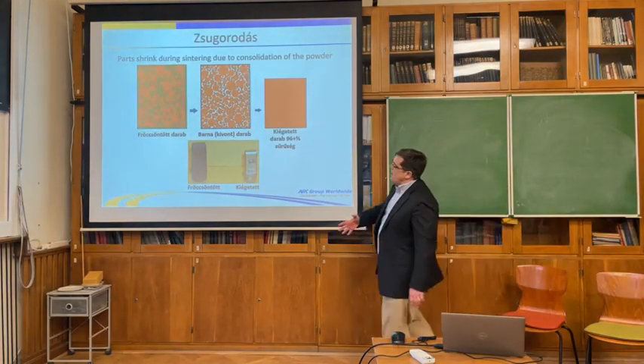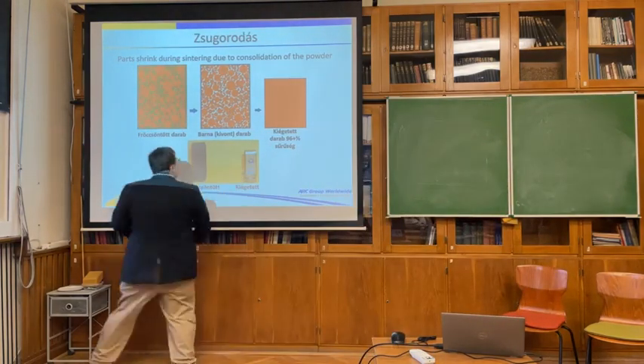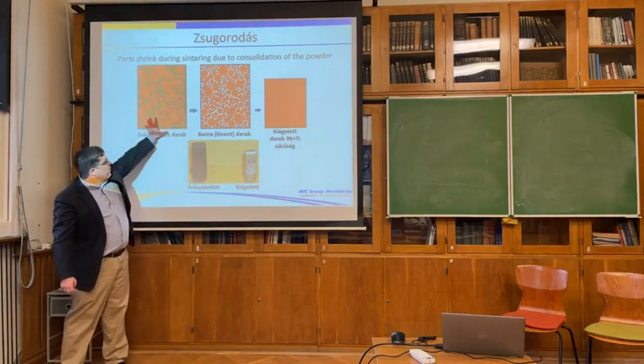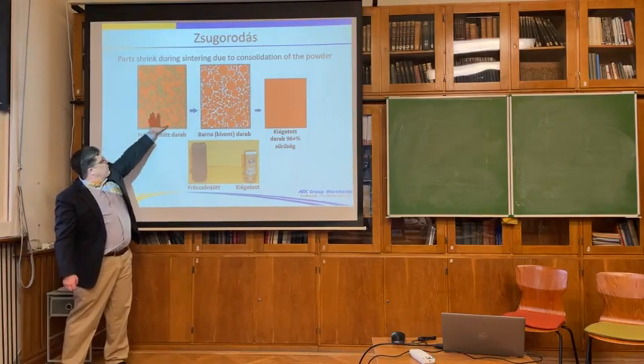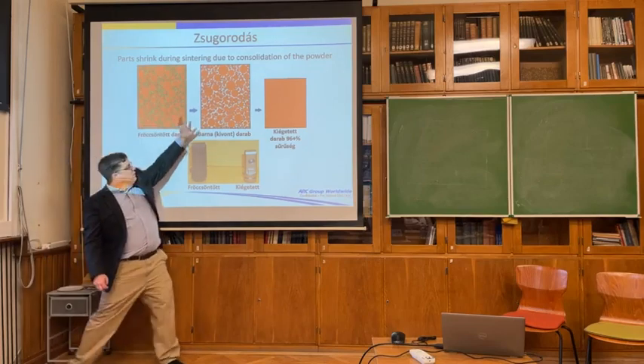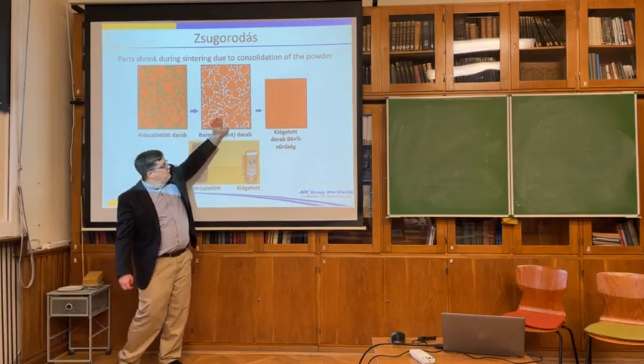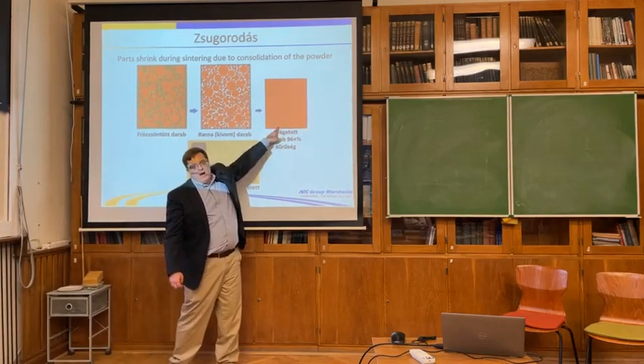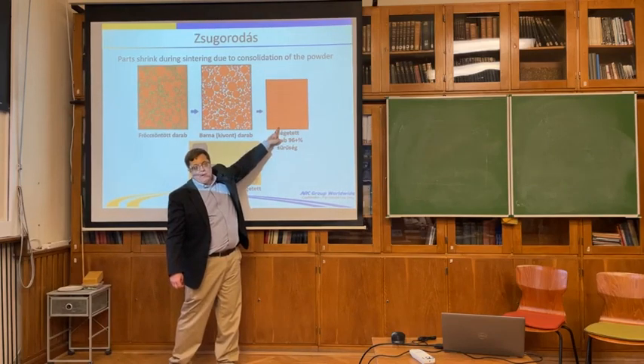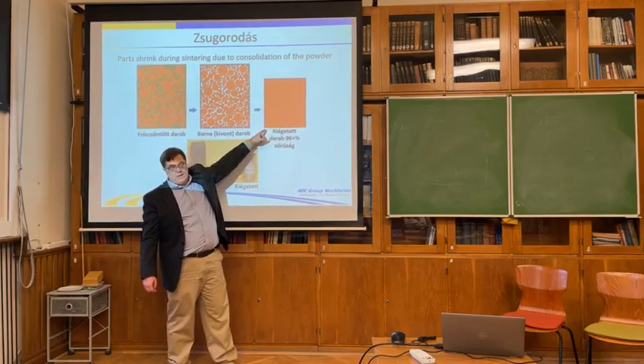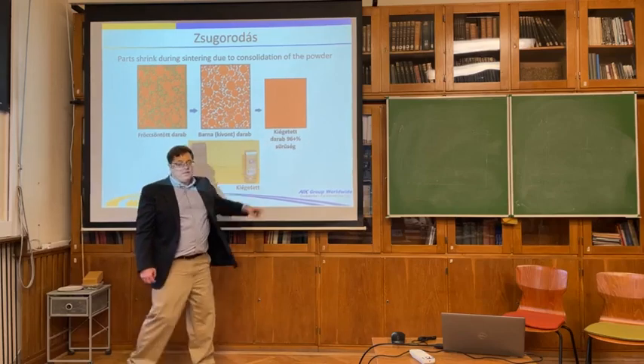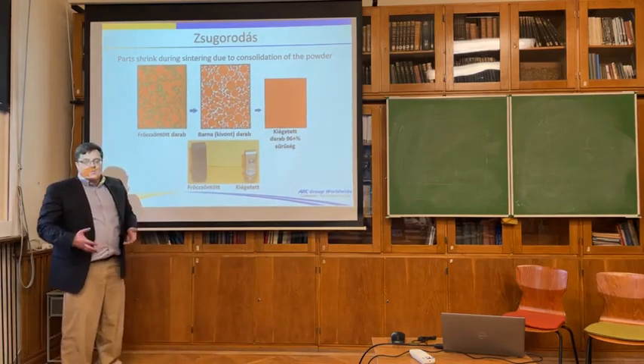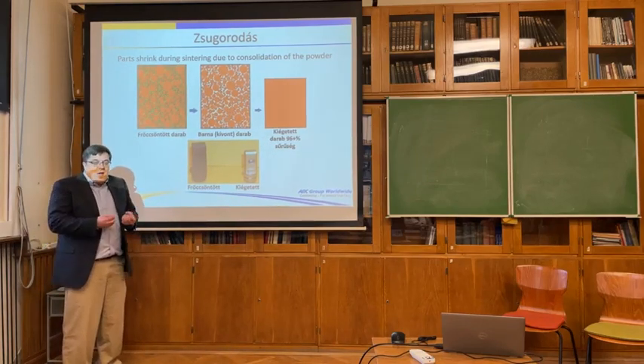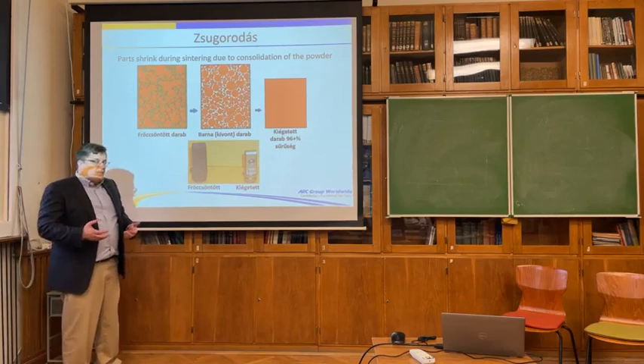So getting back to that slide, you can see this is kind of where the MIM is coming from. You have the green part, where you have the metal powder and the binder. Binder's removed here. But then this is where the shrink happens. You can see how much it gets down. And we want to get densities up to 96 to 98% dense, versus wrought or fully cast, which is 100%. So we actually get pretty close.